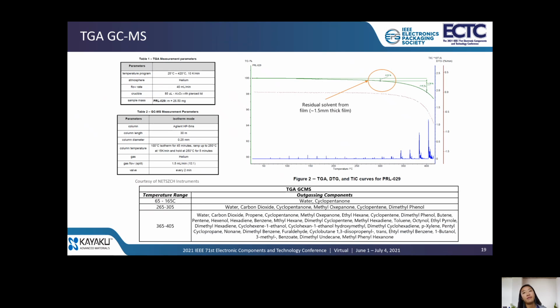Understanding the thermal stability of the material is also important for high temperature process steps and applications. For example, solder reflow steps require a preheat, soak, and reflow step where the peak temperature can reach up to 260 C all the way to 300. So it's crucial to understand the chemical components coming off at elevated temperatures and when.